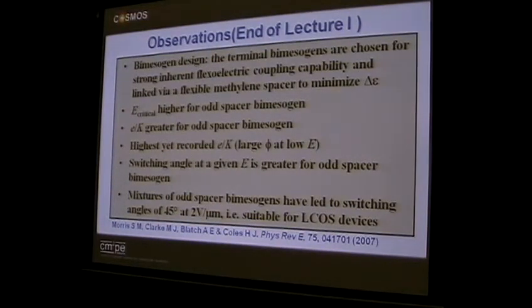You're welcome. Let me just go through them. So, by molecular design, by playing with the mesogenic unit, you can generate very high flexoelectric materials. You want to use odd compounds, odd methylene spacer unit material, rather than even. And in the conventional way you measure flexoelectric phenomena, these materials, where the director fields can deform, give you incredibly high E over K.